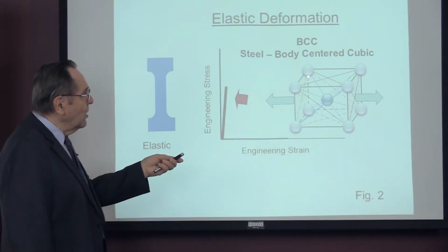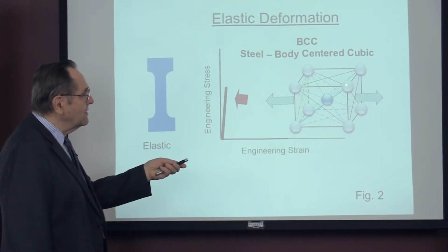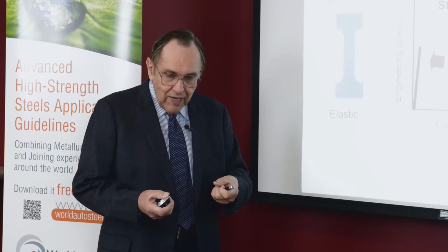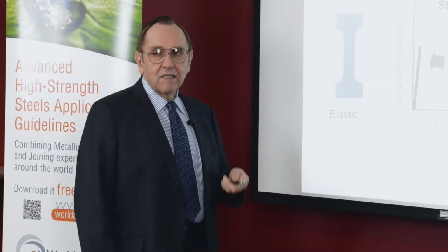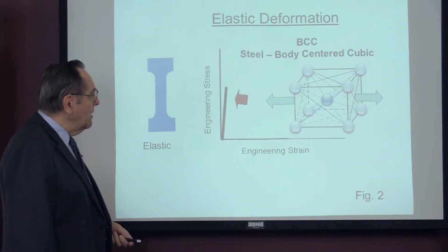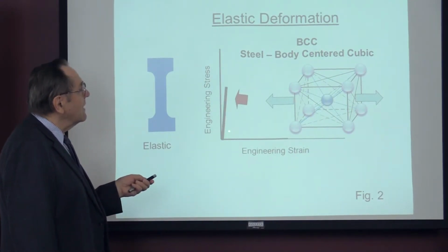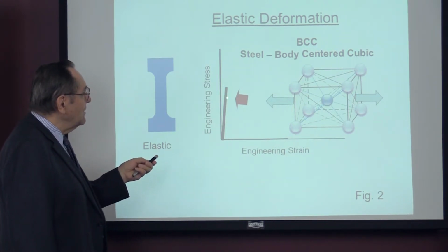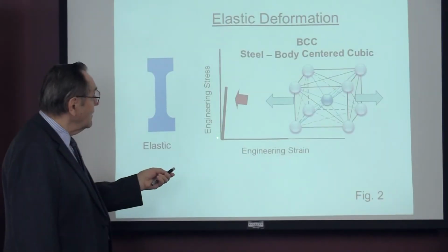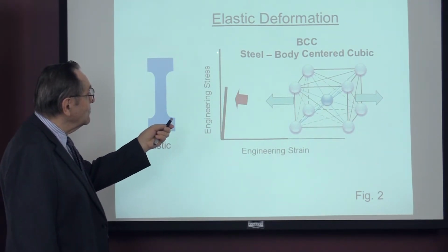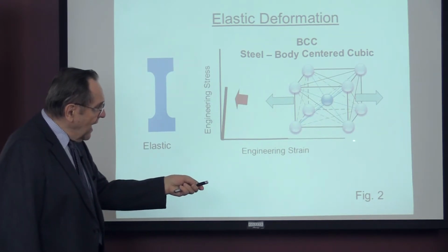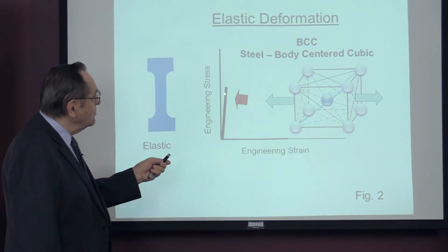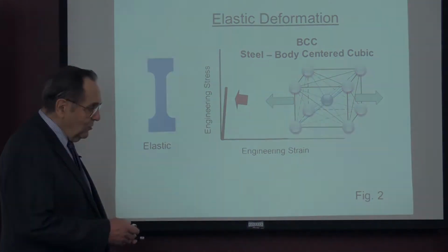These atoms are in a certain array, their distance, they are in balance, and they like to stay that way. When you start to deform metal and you start to put a force on it, the first deformation that starts is the elastic deformation, where you're starting to spread these dimensions here on your atomic cube. And this creates the elastic modulus of the steel, also called the Young's modulus. Now, normally this modulus is so strong, 30 million for steel, for example, that it comes right up this axis right here. I've elongated this axis so that we can have some tip in here so we can see what happens to this modulus as we work.